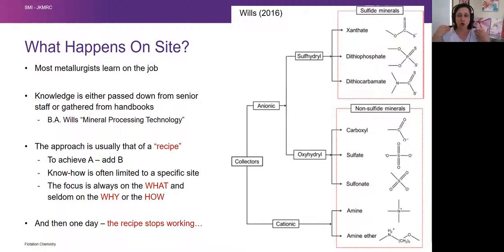The next question: is there any particular index or strength number to classify minerals to give an idea of surface chemistry? Sadly, no. When it comes to minerals, the mineral surface behavior is not inherent to a particular mineral — it also depends on the chemical environment within which that mineral exists. The type of ions present in solution matters: multivalent metal ions have a much stronger effect on the surface than monovalent ions such as sodium and potassium. Even if you're dealing with the same type of mineral such as chalcopyrite, depending on the deposit and the chemical context within which it exists, it would have different surface speciation. There is no simple index you can refer to.